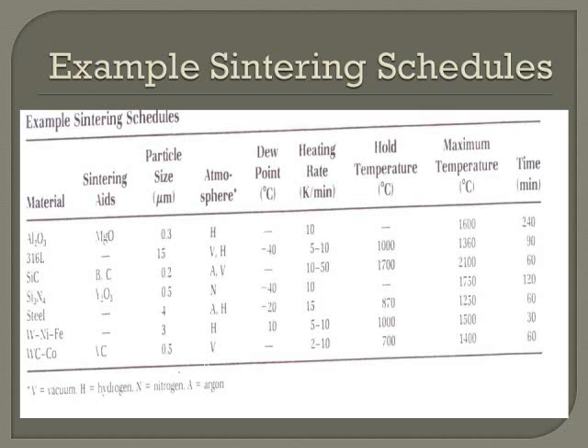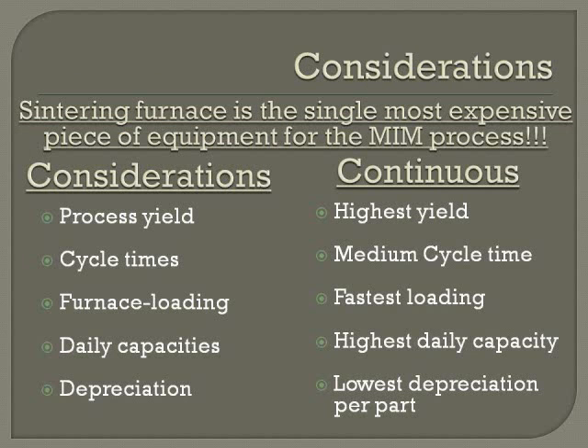After sintering, the compact has good strength and microstructural homogeneity, with isotropic properties superior to those available with many other processing routes. The sintering furnace is the single most expensive piece of equipment for the metal injection molding process. Considerations are process yield, cycle times, furnace loading, daily capacities, and depreciation. Continuous furnaces have the highest yield, medium cycle time, fastest loading, highest daily capacity, and lowest depreciation per part.